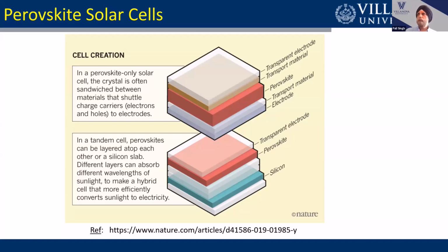More recently, there's been research around putting a perovskite on top of a silicon solar cell. So this is what's shown here. We have a transparent electrode, the perovskite structure, and then a silicon solar cell. So this type of cell is called a tandem cell. And what happens is the light goes through the top cell, and some of the light is absorbed there and converted to electricity, but not all of the light is absorbed there. And so some of the light passes down to the bottom cell. And if you optimize the design, you can get a higher efficiency of a solar cell when you have this tandem configuration than just having a single cell configuration. So I'm going to describe the advances in both of these technologies, the perovskite only and the tandem cell.